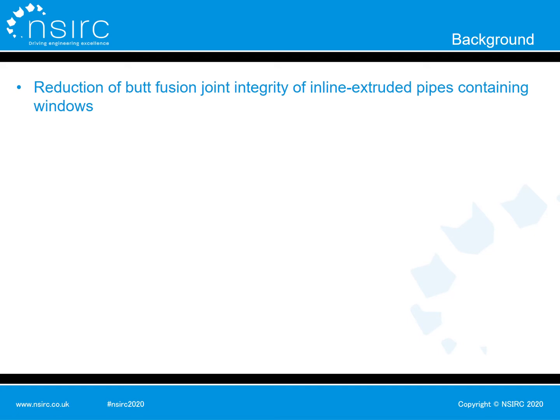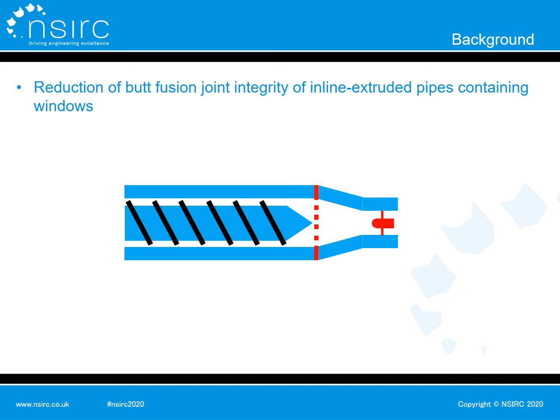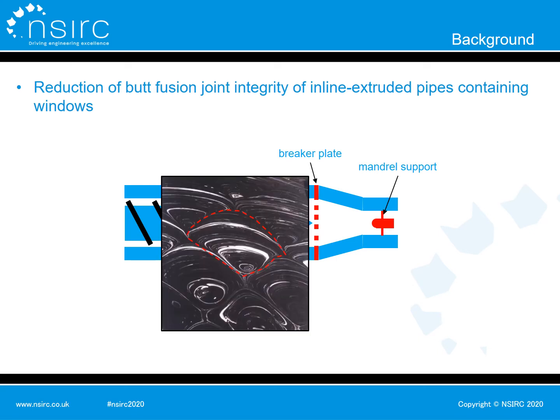In addition, poor welding between melt strands may be a reason for the reduced joint integrity as well. In single-screw extrusion, the molten materials are unavoidably separated into melt strands by flowing through some parts like a breaker plate or a mandrel support. For example, in this picture, each sector is a melt strand generated by flowing through a breaker plate. Then these melt strands will be welded together when flowing further away. If the welding of these melt strands is poor, the joint integrity of this pipe may be influenced.